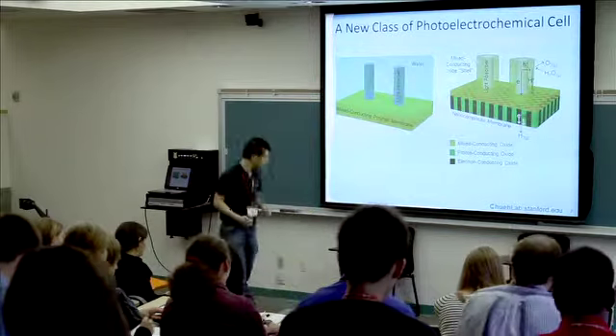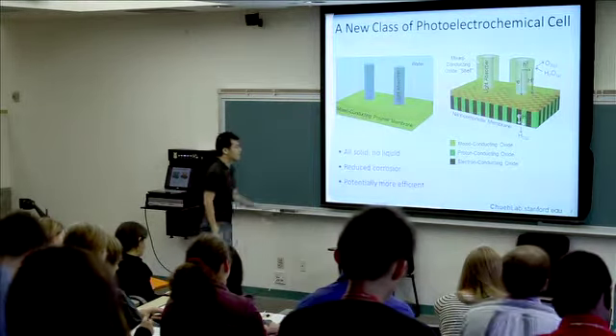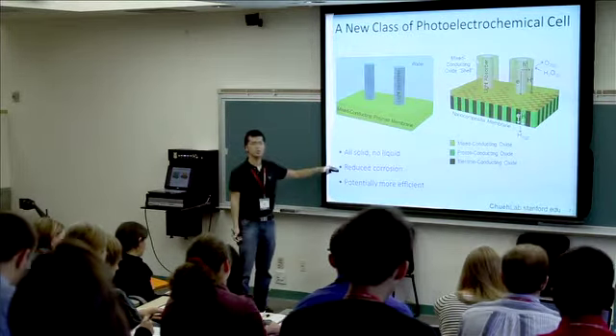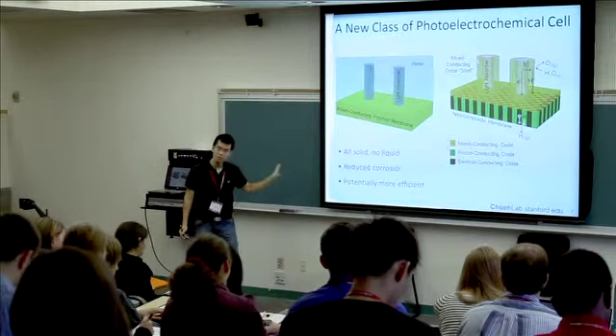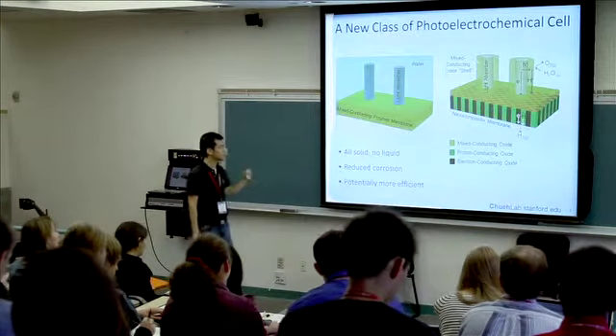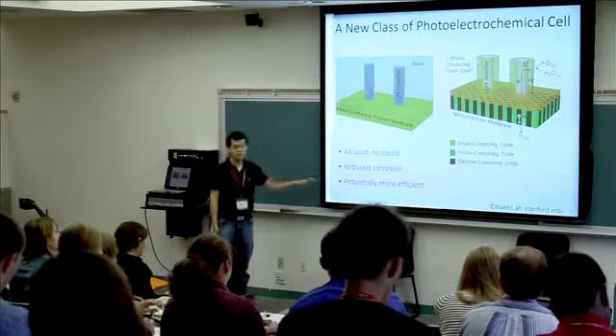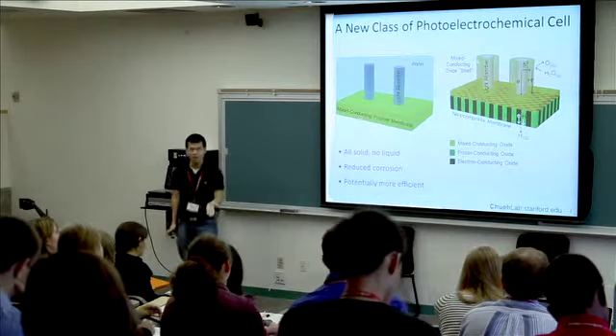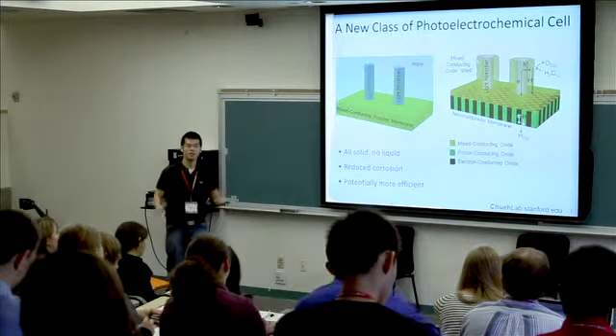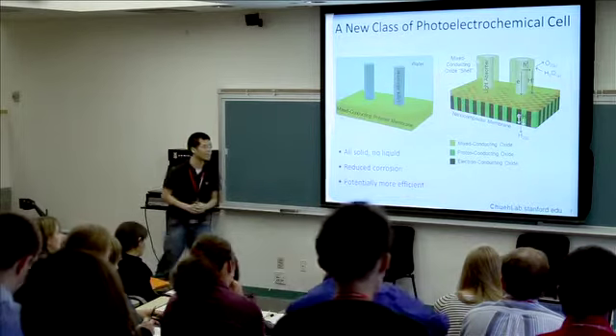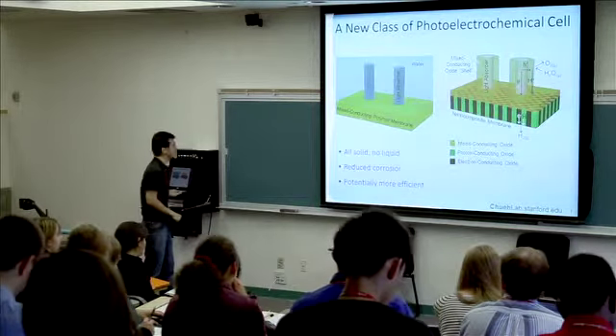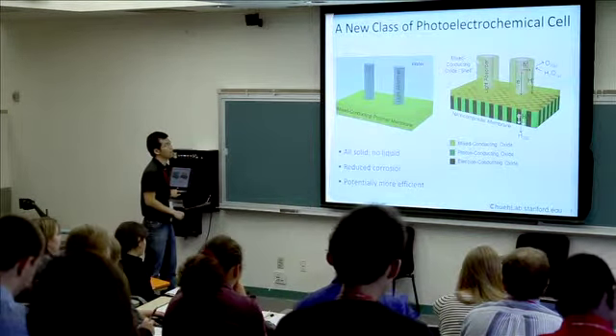So it's a fully solid state device. There's no liquid involved. There's reduced corrosion problem. There's still some corrosion problem with the gas, but much less than in the liquid case. And it's potentially more efficient because we're utilizing the energy that otherwise would have to be taken away to cool down the device. So this is a potentially interesting way to develop a new class of cell.